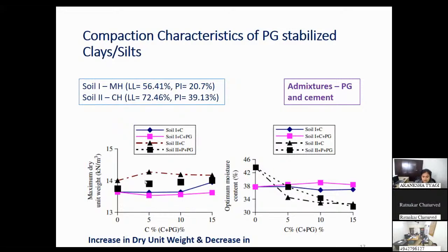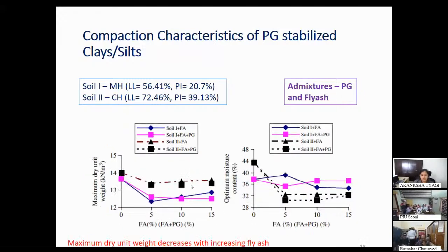And the results when they mixed cement and the results when they mixed 50% of the phosphogypsum were quite close to each other. The other thing to notice from this study is that on silt, the effect on the maximum dry unit weight was not as much as for the clay type of soil. So clay type of soil is more responsive to the addition of the phosphogypsum, or even to the cement, I should say.